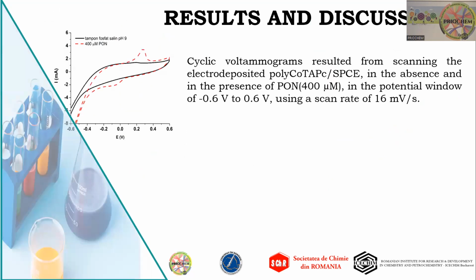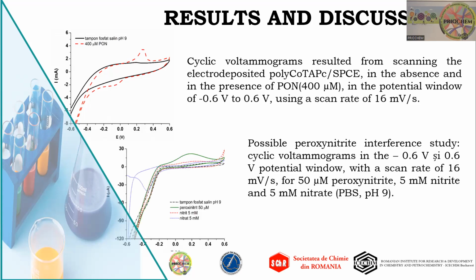So first, I studied the peroxynitrite reduction using cyclic voltammetry with the presented electrodes deposited with polycobalt phthalocyanine tetraamino on screen-printed carbon electrodes, in presence and in absence of peroxynitrite. And we can observe, in red, that we got some oxidation around 0.2 volts and some reduction around minus 0.1 volts in this specific window and this specific scan rate. I went further and studied different possible peroxynitrite interferences in the selected range,